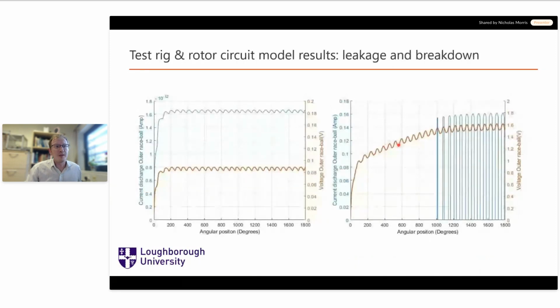These ripples that we see here are based on the vibration of the shaft and aligned to the ball pass frequency. So each time one of the rolling elements moves underneath the load, it provides a small kick up to the shaft, and a bit of additional force from that case, until the next ball or rolling element passes under the shaft and then gives it a kick. Each of those kicks create this vibration on the shaft. They slightly change the film thickness, slightly increase the field strength, and then we get the discharge that we see in each of these locations.